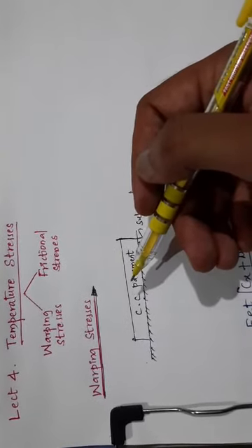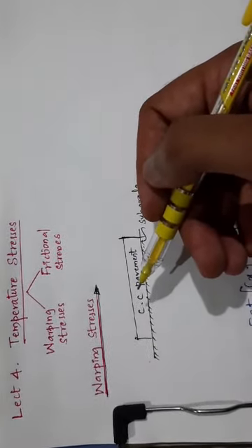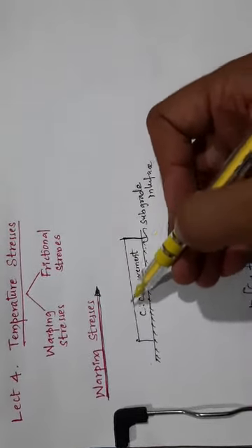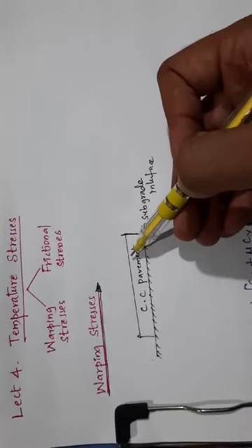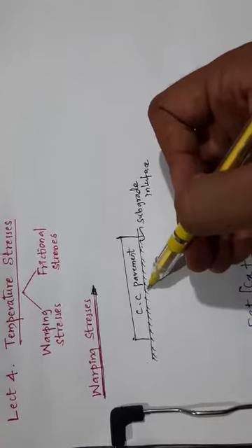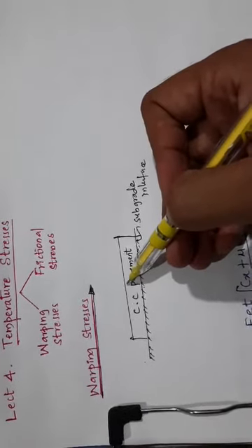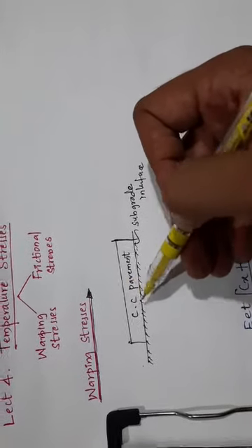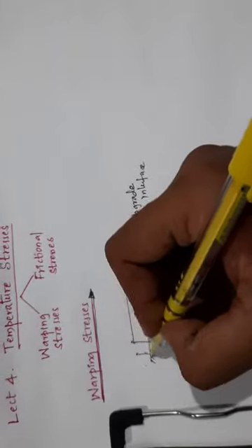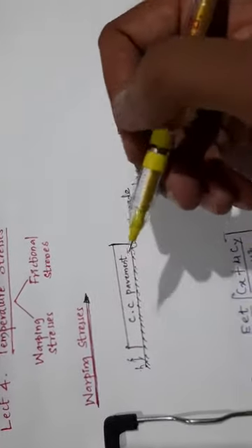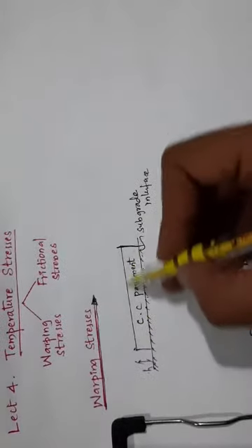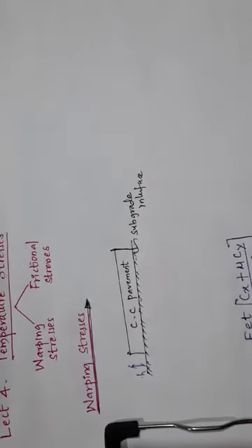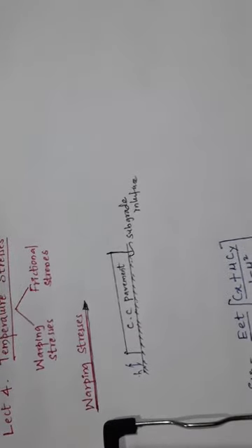and the locations. So the warp stresses during the day: the top of the pavement slab becomes hotter under the sunlight while the bottom of the slab still remains relatively colder than the top, resulting in a temperature gradient throughout the depth of the slab. So this results in expansion of the top slab with respect to the bottom.